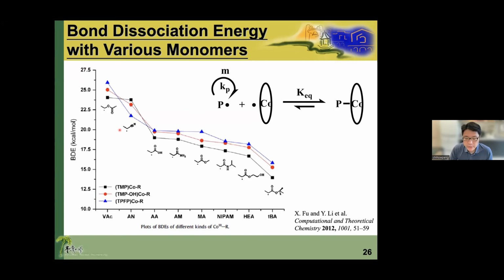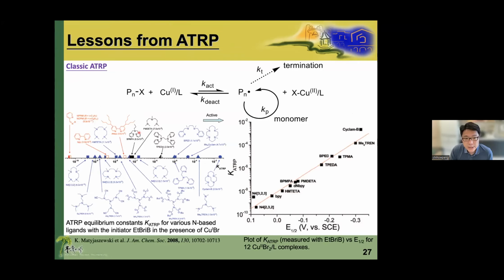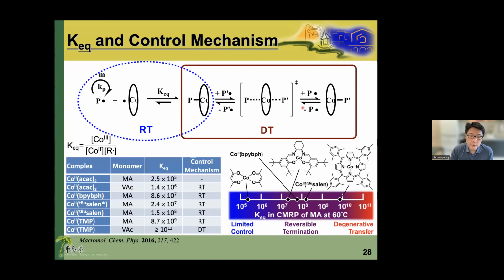Because our equilibrium is the cobalt-2 and cobalt-3 equilibrium, it's similar to the ATRP system, which has the copper-1 and the copper-2 equilibrium. So we learn from ATRP, and they analyzed that the redox potential of the copper complexes is proper to the equilibrium of the ATRP system, because you can see in this reaction, the whole equilibrium includes the copper-1, copper-2 equilibrium, similar to cobalt. So we propose that the cobalt-2, cobalt-3 redox potential should also be relevant to the equilibrium of CMRP. So we try to reorganize the system, and we collect the data of different monomers, measure the equilibrium constant,